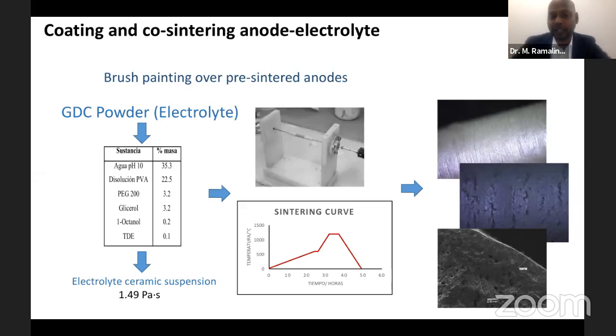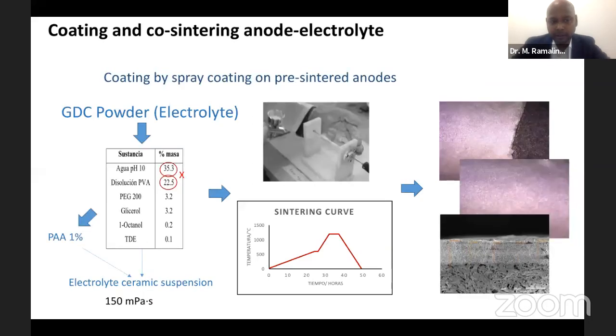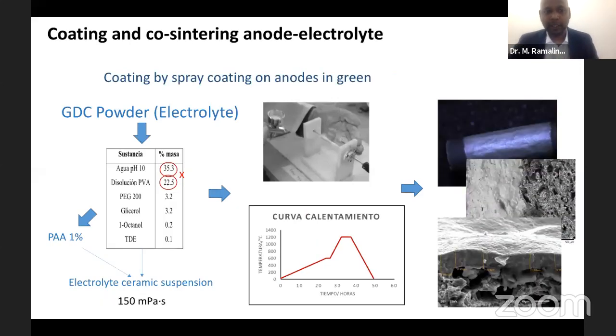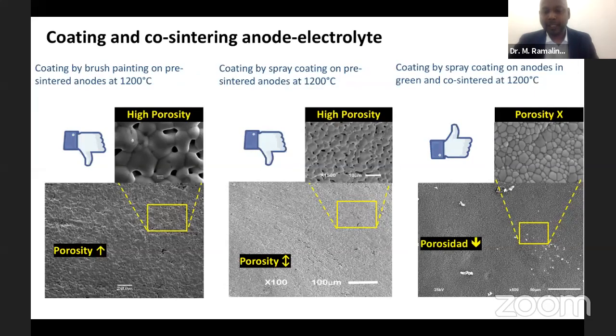In that case, we also developed laboratory scale brush painting of this material, using spray coating that we coated over the anode tubes that we fabricated. Those tubes you can see here in white color, and after coating, we sinter this material